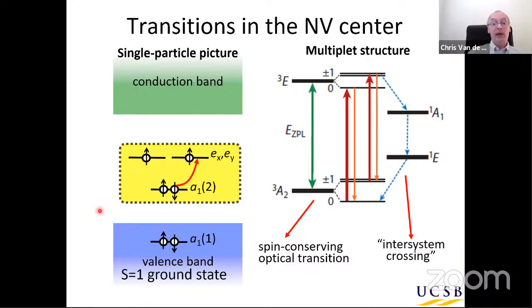Once we have the correct charge state, the correct spin state, we can look at optical excitations. Okay, and in order to analyze that in detail, I won't go into that in this talk. You actually look at multiplet states, but the basic issue is that you use light, absorption of a photon, to excite an electron out of this ground state level into an excited state. Okay, and that takes approximately 1.9 electron volts. During the excited state, the electron can come down again to the ground state. These transitions, these optical transitions of absorption and emission, are spin conserving.